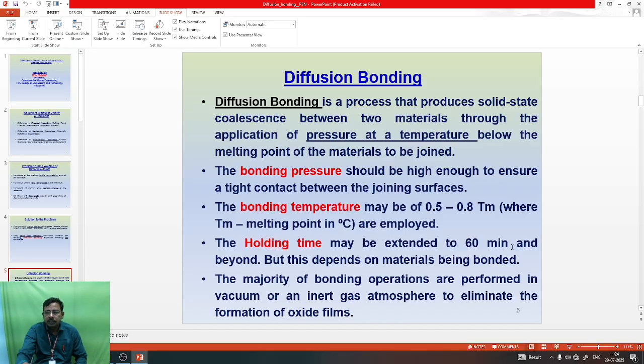Diffusion bonding is a process that produces solid state coalescence between two materials through the application of pressure at a temperature below the melting point of the materials to be joined. Diffusion bonding consists of three parameters: bonding pressure, bonding temperature, and holding time. Bonding pressure should be high enough to ensure tight contact between the joint surfaces. If the pressure is less, the metals cannot be fixed tightly, so diffusion between the surfaces is very little. If high pressure is given, the edges of the metals bulge. So suitable pressure should be applied when the diffusion bonding is going on.